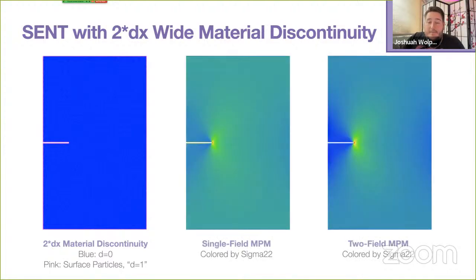And here on the right side, we visualize the tensile stress field resulting from simulating this specimen with both single-field and two-field MPM. And as you can see, single-field MPM struggles to capture the traction-free crack surfaces, even with this explicit discontinuity. And conversely, two-field looks to be nicely capturing this traction-free surface.